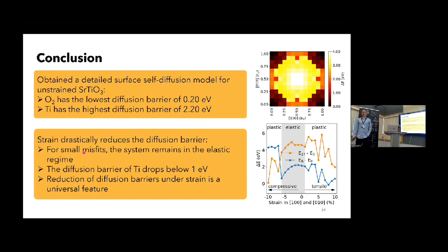Okay, then allow me to go a bit further. Why are you so sure you have titanium dioxide? I know that there is a big plane where those terraces are titanium dioxide, but there is an equal plane that is always strontium oxide there. Of course, we are able with measurements to determine the surface termination. With what measurement? Tip-enhanced Raman spectroscopy. There you are able to really measure the surface termination.